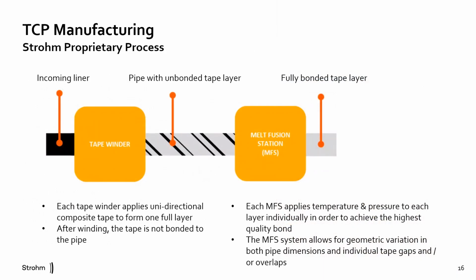In each of our production lines, we have a series of tape winders, and then what we call melt fusion stations, or MFS. The polymer liner is made on our extrusion line and sent to a carousel for storage. When it's needed, it's fed through to our tape winders, where the composite tape is wound at a specific angle to give the desired properties. At this point, we're not too concerned about micron perfect tape placement, as the system is fully capable of dealing with gaps and overlaps within the individual tape layers. The key is the angle.